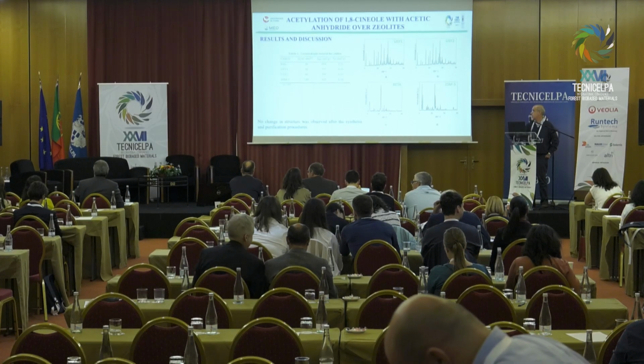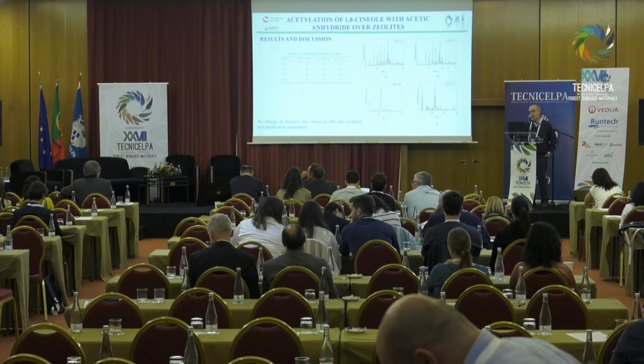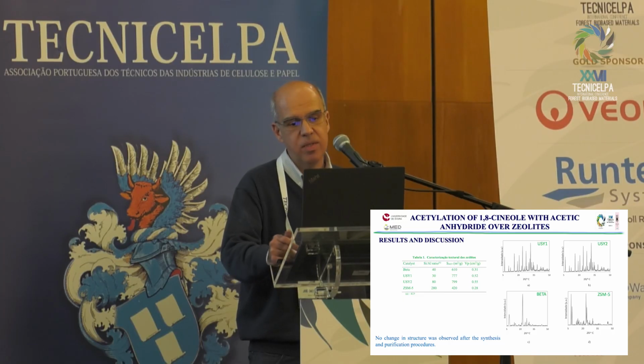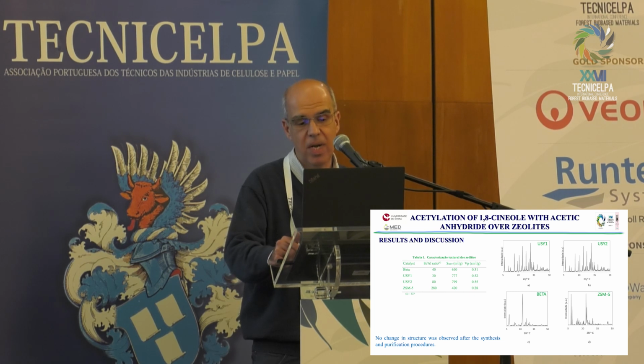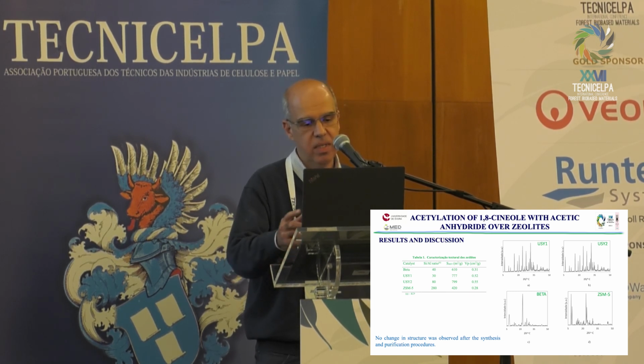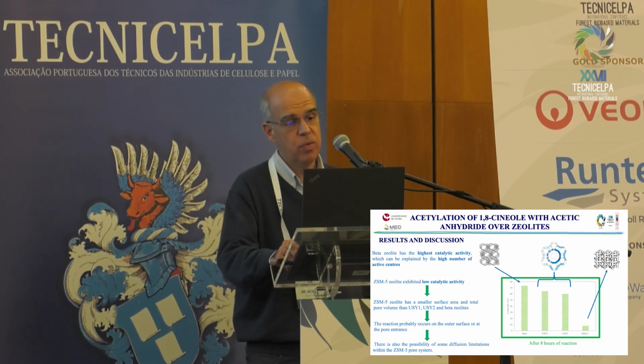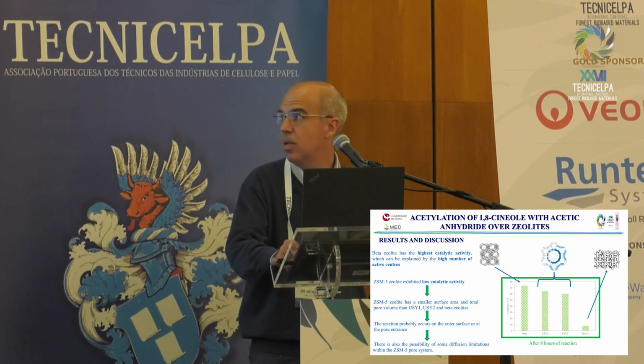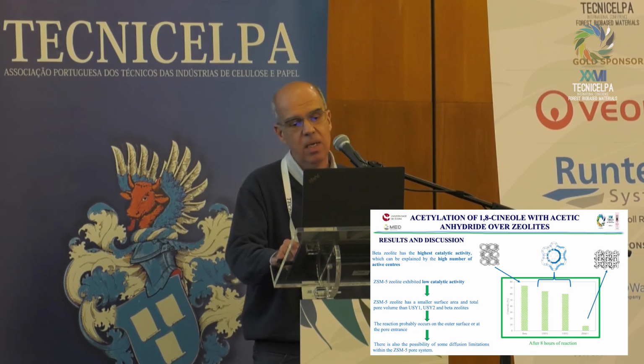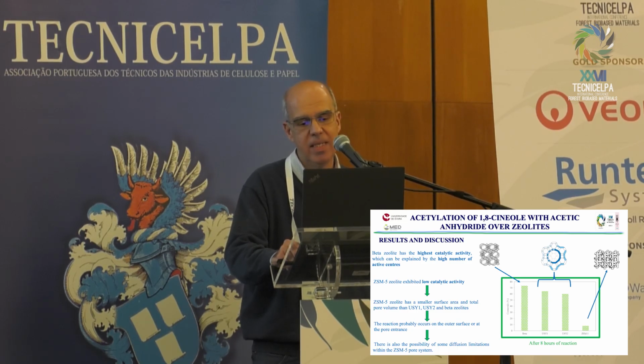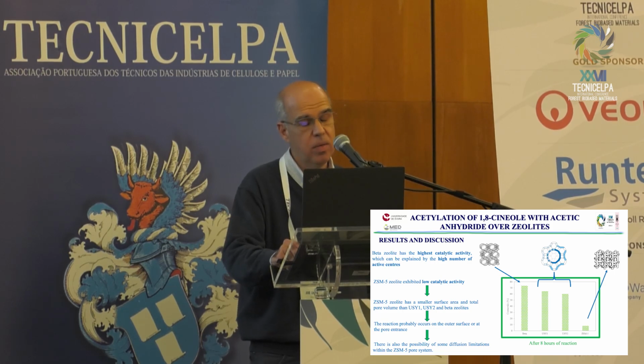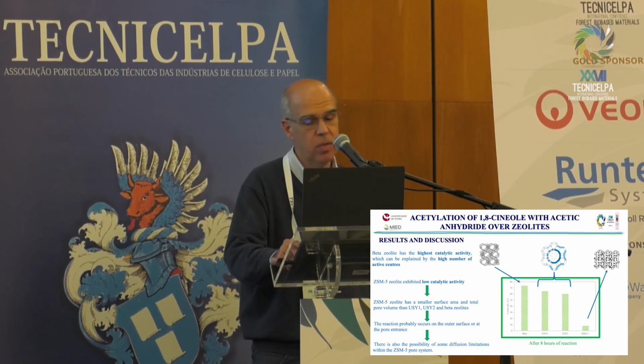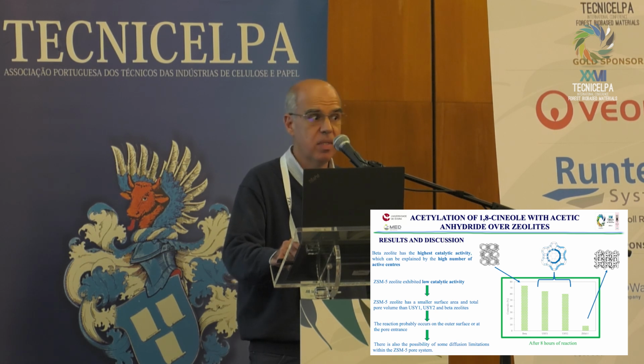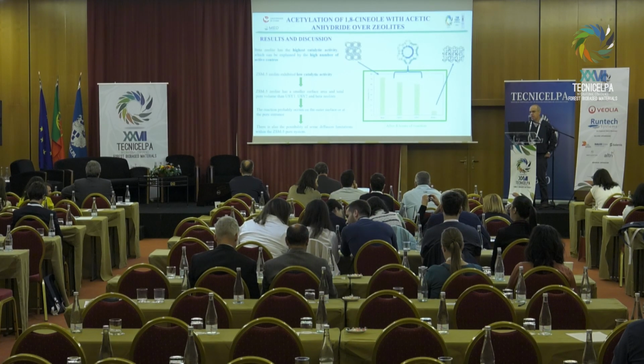This is our characterization. The zeolites are microporous materials, with a high surface area. After the preparations, the structure is similar. There is no observable change. And when we use them as catalysts, you can see the beta zeolite shows high catalytic activity, while the ZSM5 has low catalytic activity. Maybe it could be due to the low surface area and pore volume. And sometimes it's possible there exist some internal diffusion limitations inside the porous materials.